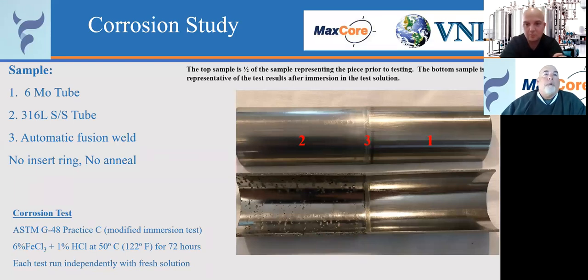What good does it do to spend $20 for a weld insert ring when your base metal is going to corrode once it gets past that? So my point in saying this is no, you don't need a weld insert ring. What you need to do is make this joint in a location outside of your corrosion issues before you do this type of weld. And then you're going to get enough of a material interface on this weld area from the over alloyed material in the AL6XN to the 316, you're going to get enough homogenization from these higher alloys in the AL6XN to improve that weld area over the 316 in that particular area.